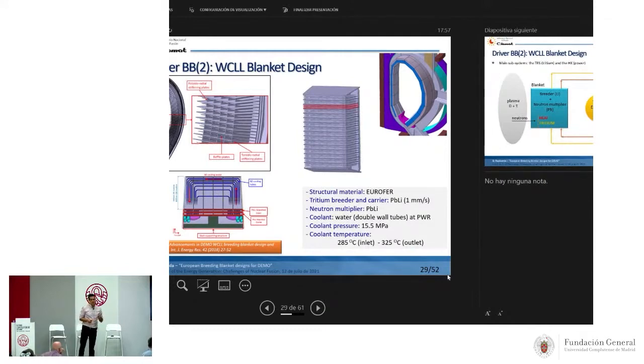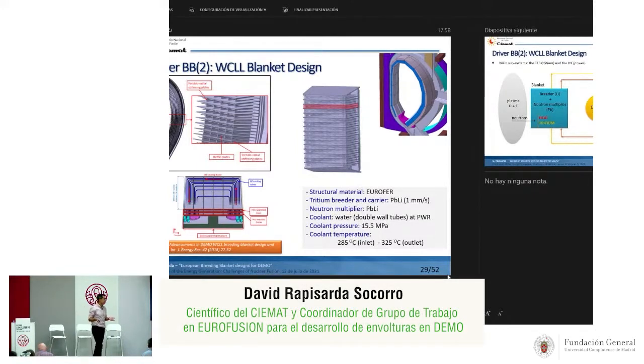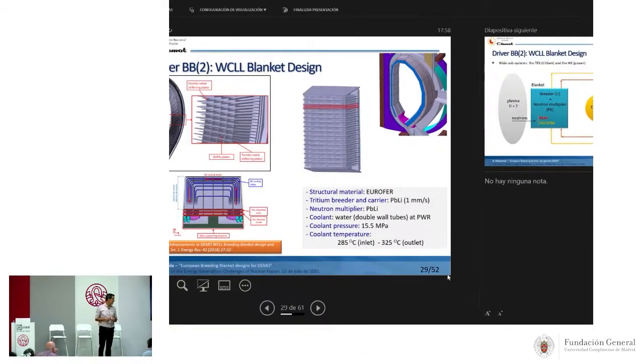And for the coolant, which is water, and this is quite important, we use double-wall tubes. Why? Because we don't want the lead-lithium and the water to interact. So we need a double wall to avoid, imagine if the first tube is broken, you can spill some water into the lead-lithium. So we put two tubes, one inside the other, to avoid this problem. The coolant pressure is 15 megapascals, and the temperatures are slightly lower, 285 degrees at the inlet and 325 at the outlet.